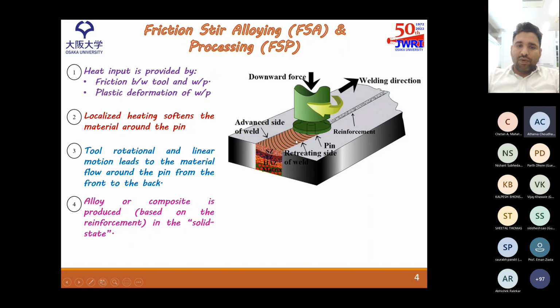And in this way, the localized heating is generated, which softens the material around the tool pin, and this rotatory motion makes the material flow. And in this way, the reinforcement material in the groove gets filled and mixes with the base material. And in this way, the alloy or composite based on the reinforcement is produced in the solid state.